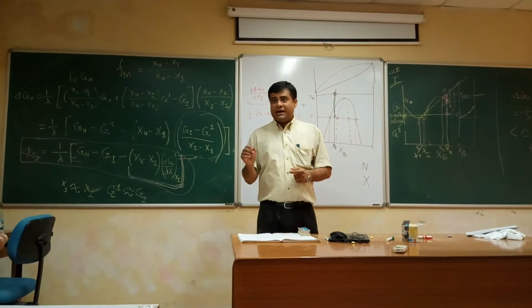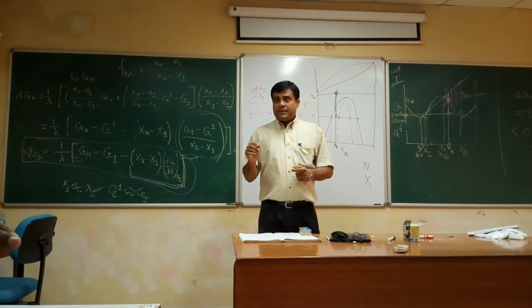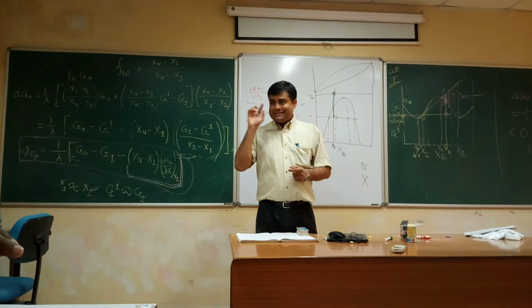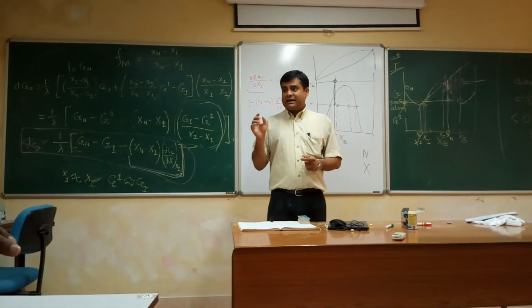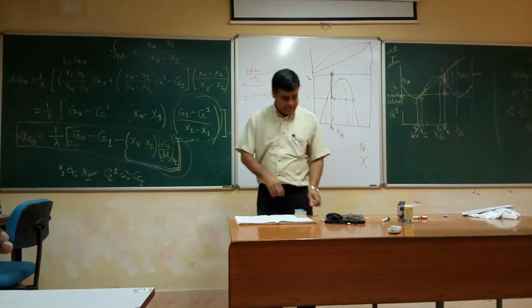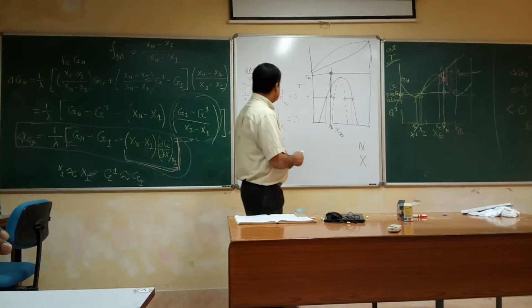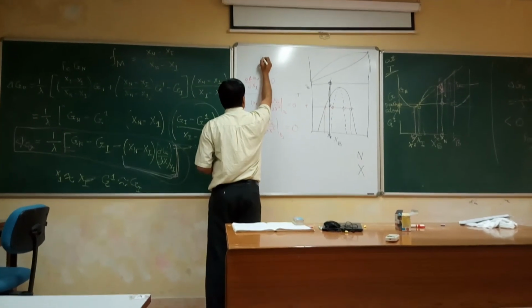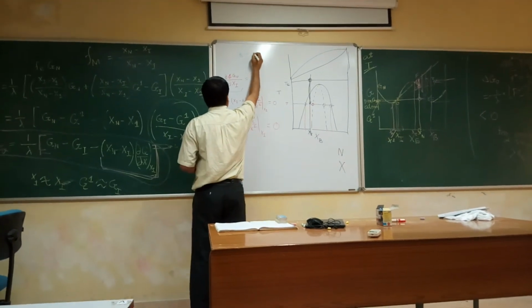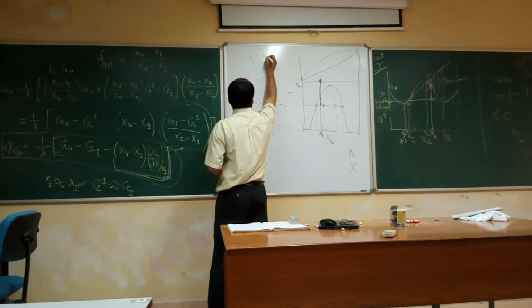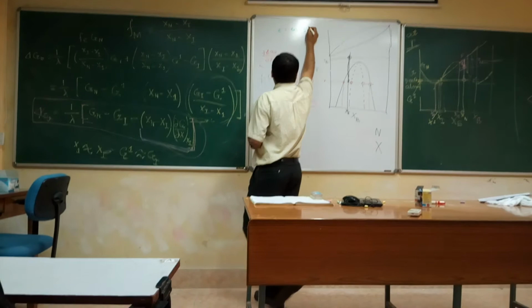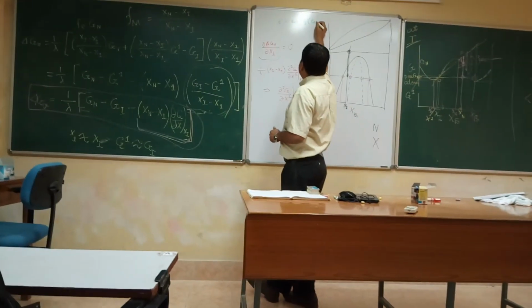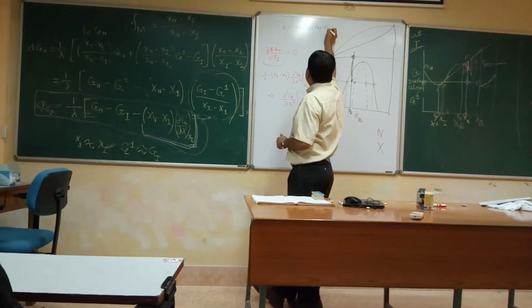That omega contains the interaction parameter, z times the difference in bond energies, which was epsilon AB minus half of epsilon AA plus epsilon BB.